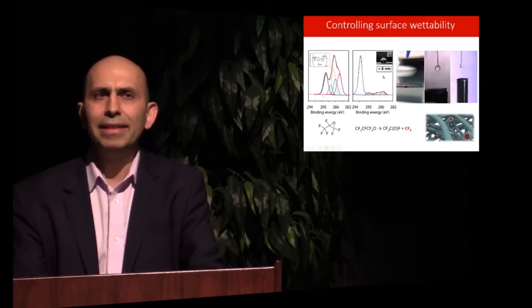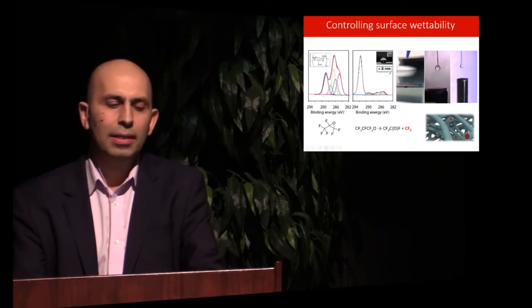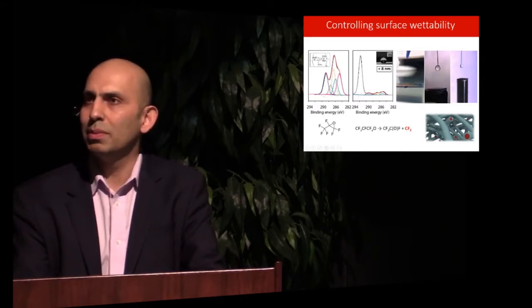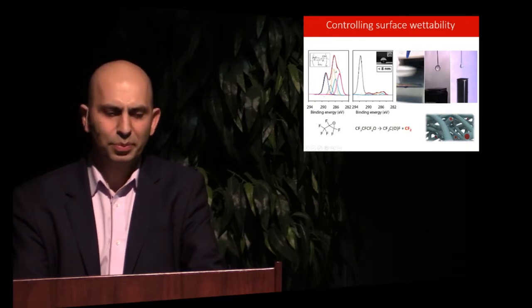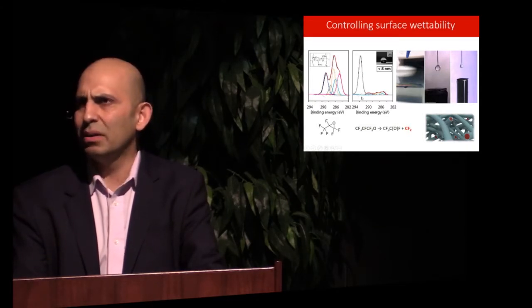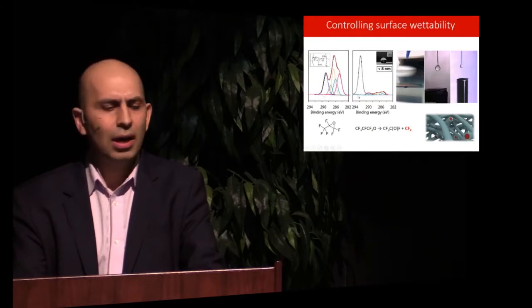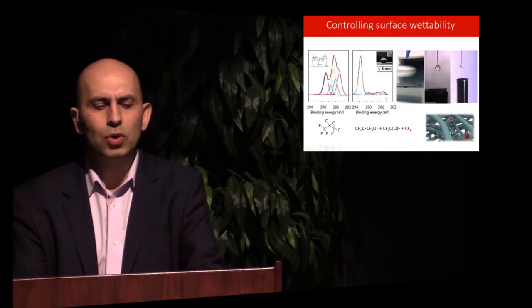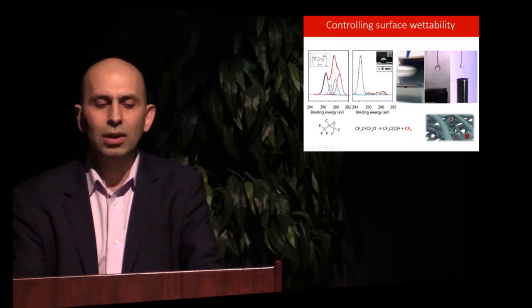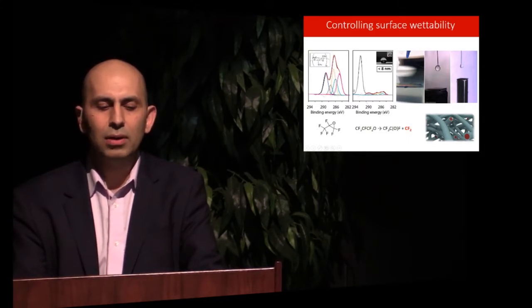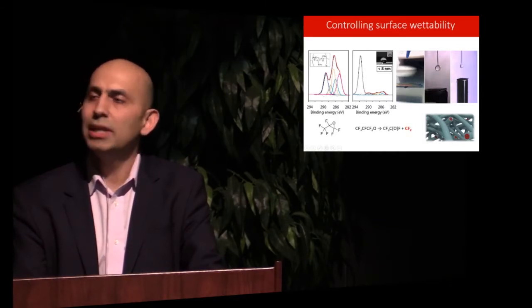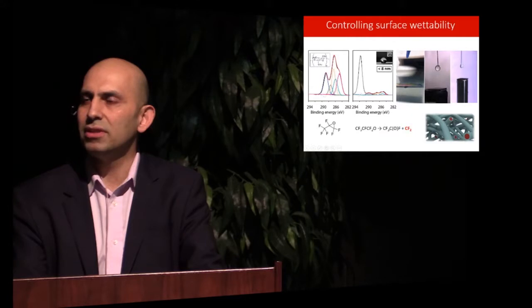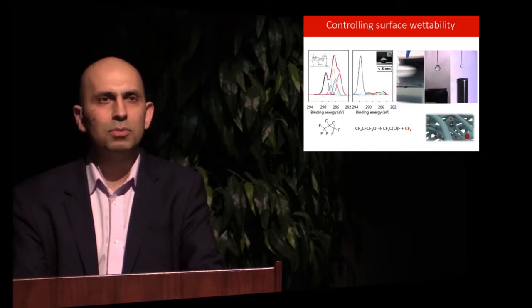Here I have a less than 8 nanometer coating that I added through this chemistry to the top surface of the cellulose acetate membrane. Here's an electron spectroscopy signal. Here's the cellulose acetate, and you see that the signature of cellulose acetate still is in the signal. And here's the CF2 band, which is a result of adding that CF2 on the top of that layer. As you see, the water doesn't even wet the surface. So we can adjust the surface property easily.